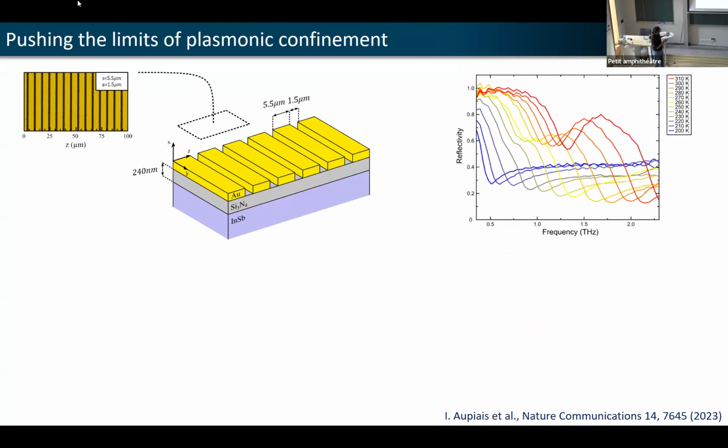And this photon, typically around 1 terahertz, will get confined to this 5.5 micron stripe, 240 nanometer dielectric thickness, and the plasmonic material. So it's really, really small cavities. Actually, we've made also 2D cavities. And in this type of system, we can basically squeeze the terahertz photon in terms of volume to 10 million times smaller than we can get in free space. So that's the nice thing of plasmonics, that you can really confine.